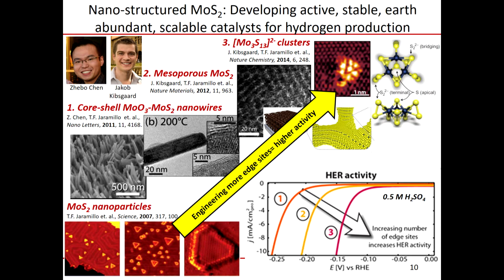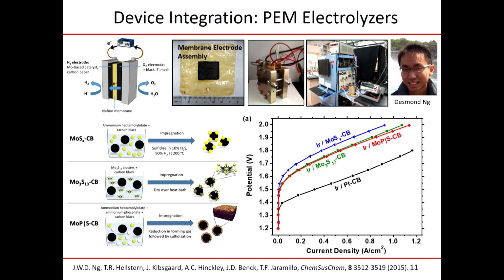They're showing activity. One of the challenges is that in this case, we were doing things in a very fundamental way, which is great to get some information, but we're running about 10 milliamps per square centimeter. I should be clear, these are not as good as platinum. No human on Earth has ever made a non-precious metal catalyst that's as good as platinum. But we're getting somewhere. And the question is, what can we do from there? And so we translated this. This is the work of Desmond, a further PhD student along the program, who then took a lot of these formulations of sulfides and phosphides and phosphosulfides and made them into inks.